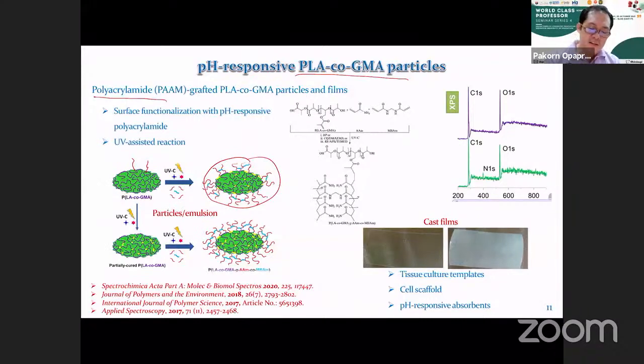We can then cast this into film, and we can see that the film that we get from these particles without grafting of polyacrylamide is quite clear, but with the grafting of polyacrylamide, they become a little bit more opaque. And they respond to pH very well, and also respond to the temperature as well. So this has high potential for use as a tissue culture template, or cell scaffold, or can be used as an absorbent that has pH responsive function.